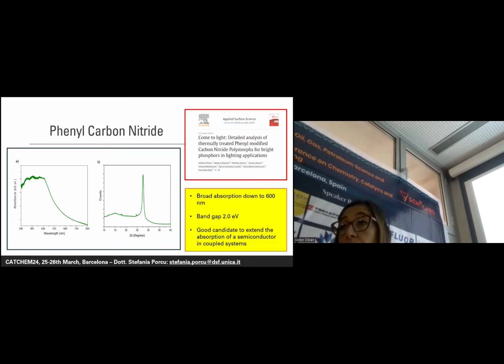That it's very promising for photocatalytic application because it covers a good part of the visible light absorption. For what concerns the X-ray diffraction pattern, it is very similar to the one of graphitic carbon nitride, and we can highlight only one peak at 27 degrees that represents the distance among the planes, because it's a graphitic-like material. And we can observe a broad shoulder around 15 degrees that is attributed to the distance among the heptazinic chains.